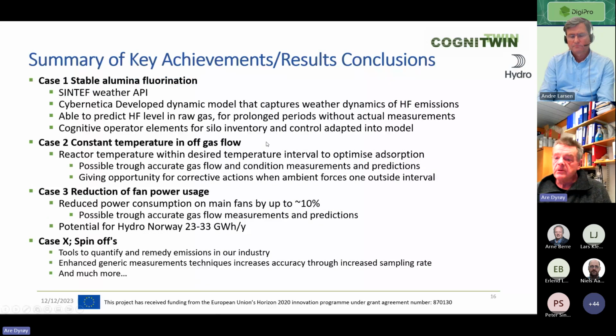So all in all, we were able to put through a stable absorption of the fluoride going back to electrolysis. It was based on the model developed by Cybernetica and the cognitive feedback from operators, combined with meteorological data that we got from the SINTEF weather API. We also saw the good effect of having constant temperature in our main reactor of the GTC, and we reduced the power usage by as much as up to 10% on the main fans that we had, giving, as I said, 23 to 33 gigawatt hours per year.